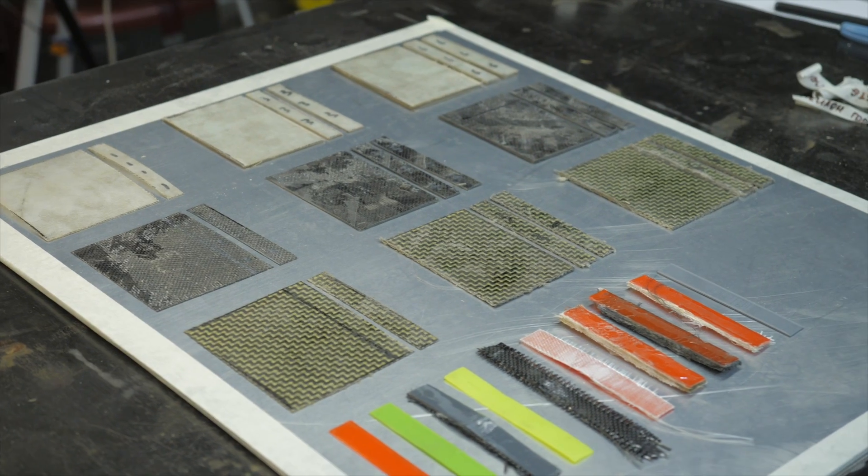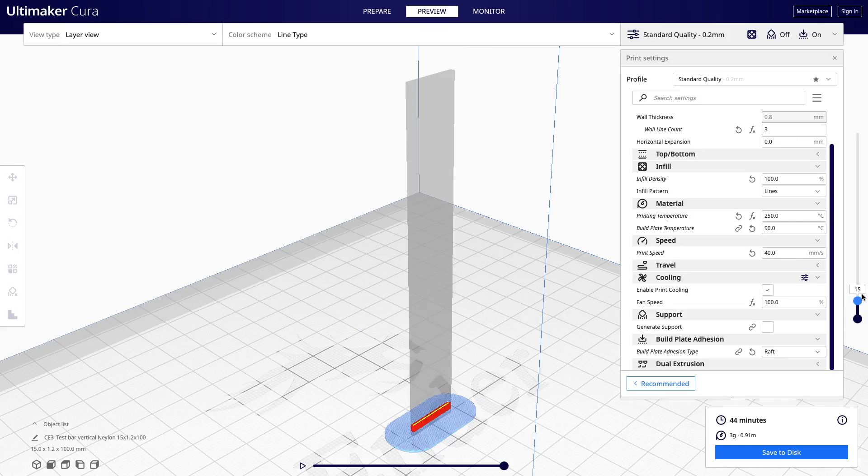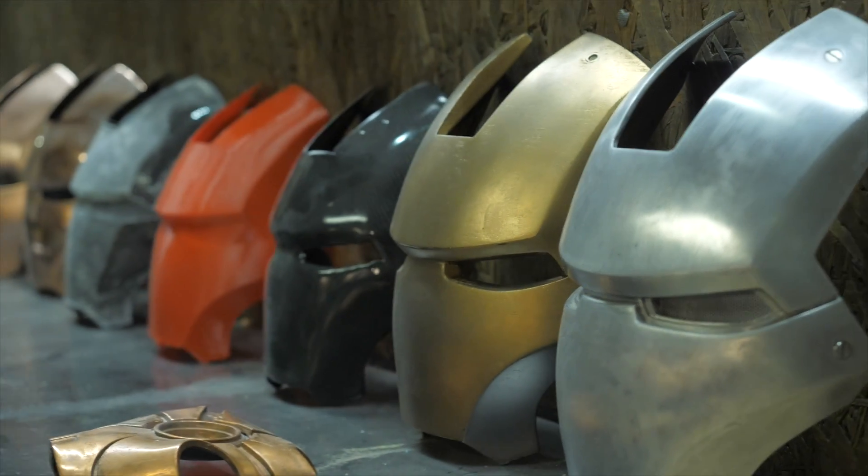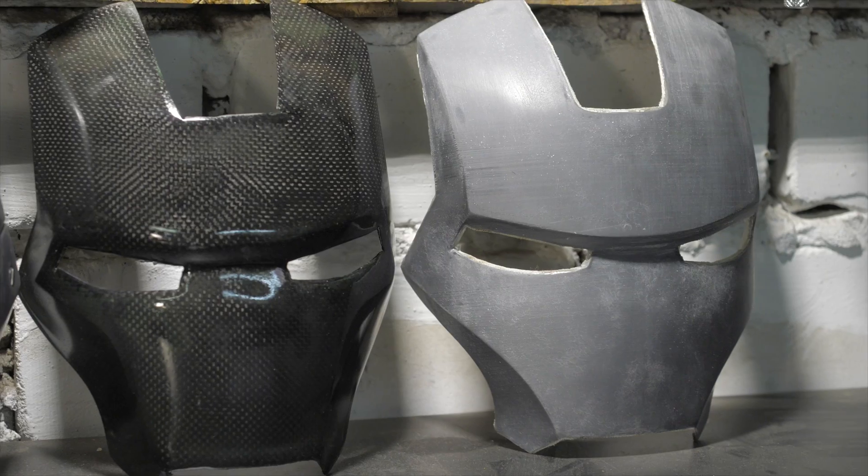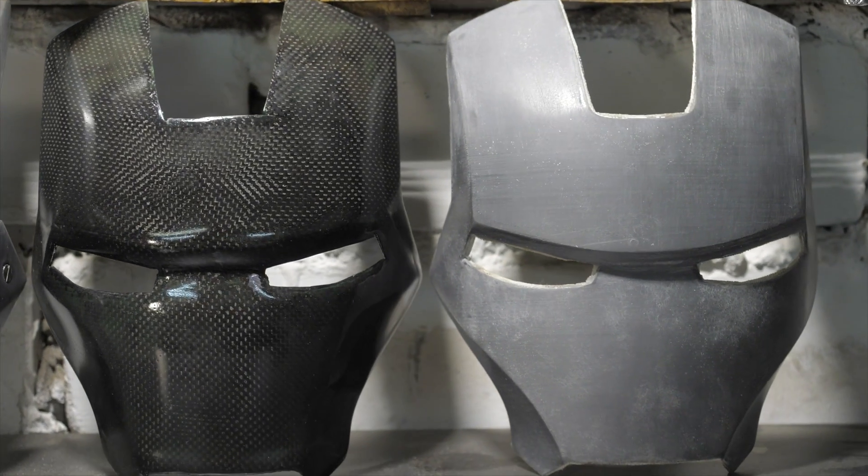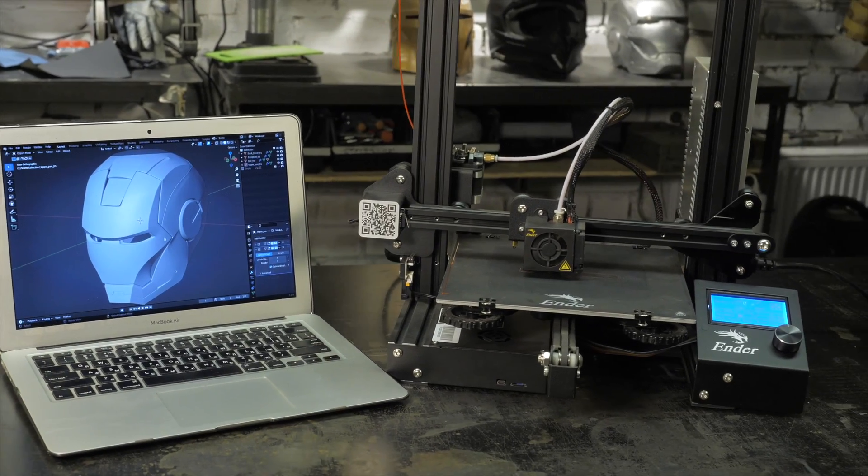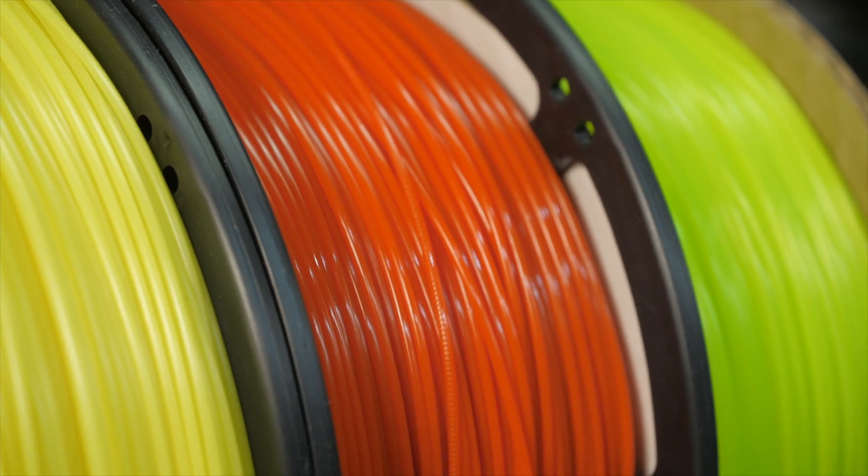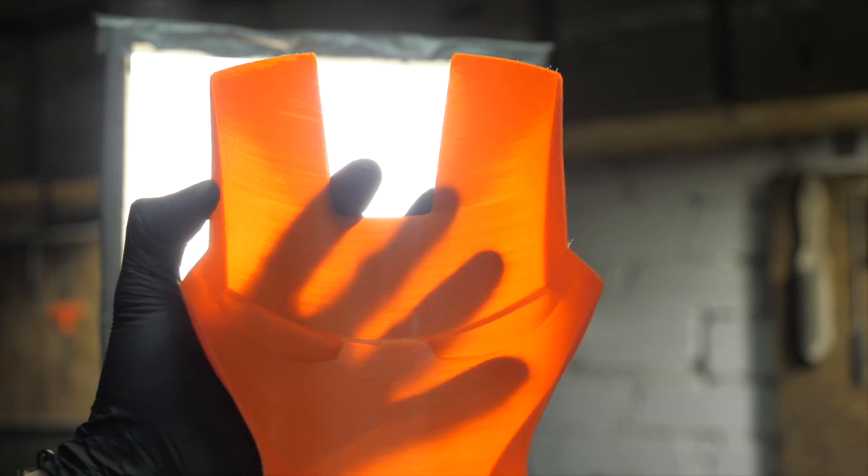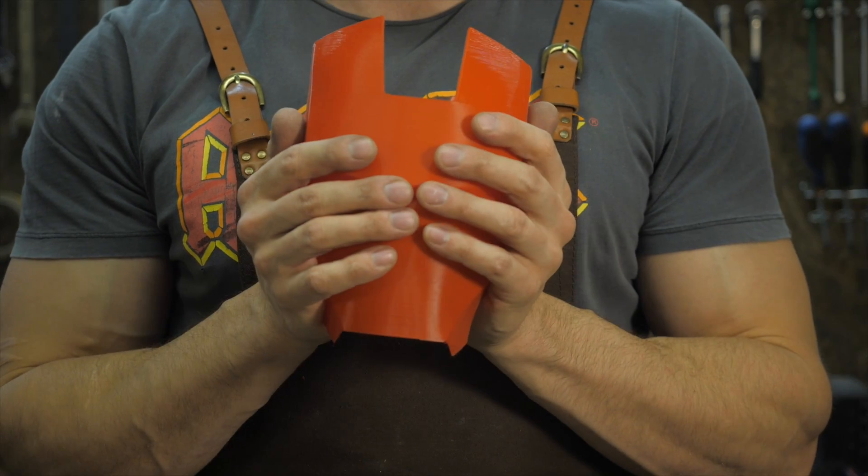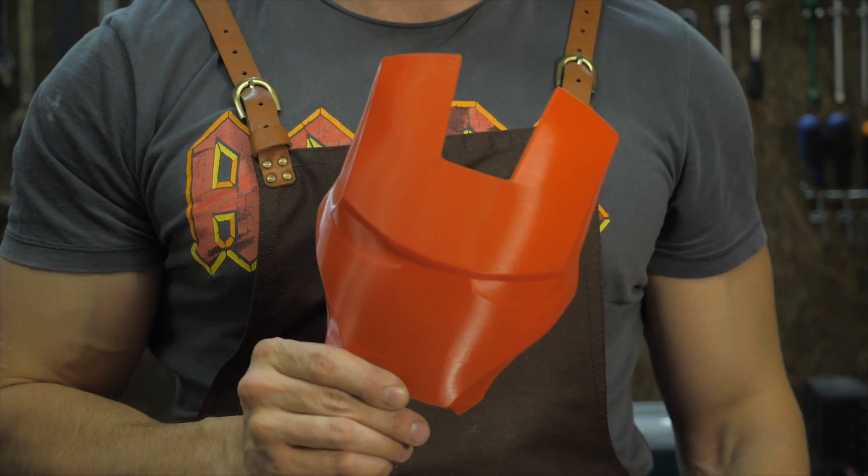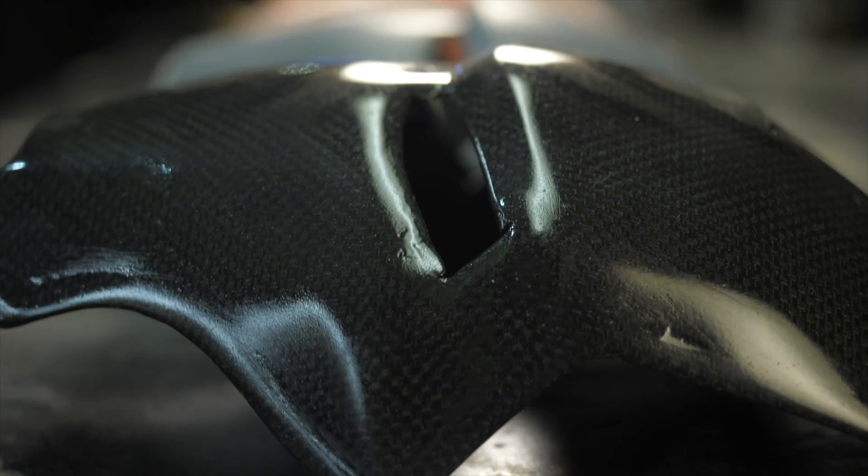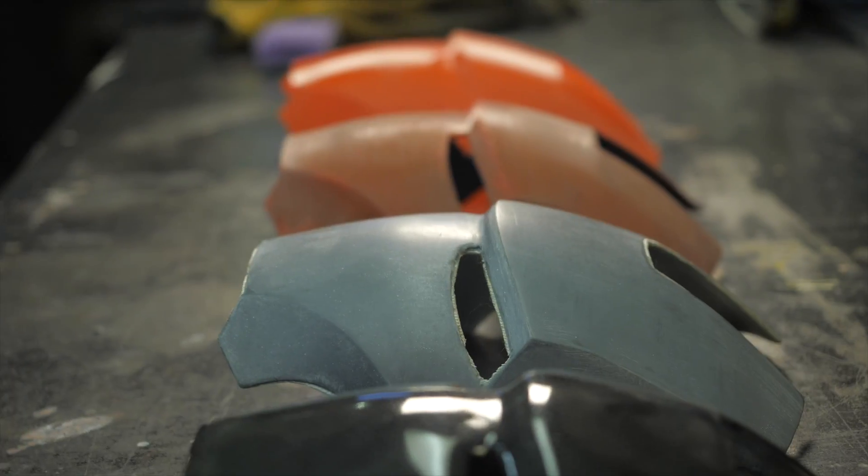After hundreds of tests with different materials, printing techniques, and all sorts of composite reinforcement combinations, here is the solution that seems to me the most technologically advanced and easiest to do. We use cheap and affordable FDM printers and basic printing materials like PLA for the manufacture of the thin matrix of the part with the strength necessary only for further reinforcement. And then we reinforce the part with composite materials to the strength required for your goals.